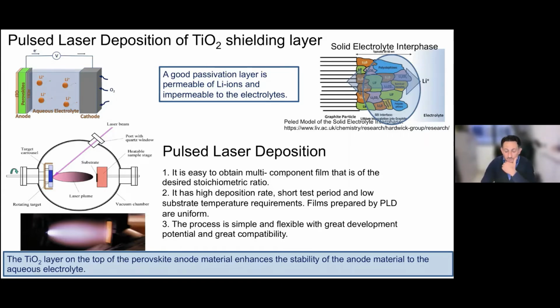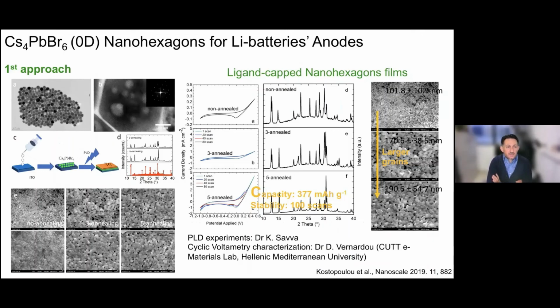So we applied this technique, and as you can see here, this is the first approach to obtain electrochemical cells using these nanohexagons. These nanohexagons were drop casted on top of indium tin oxide, and then, as you can see here, with the PLD we deposited the titanium oxide layer. Then, to improve the integrity of the anode, we applied an annealing process.